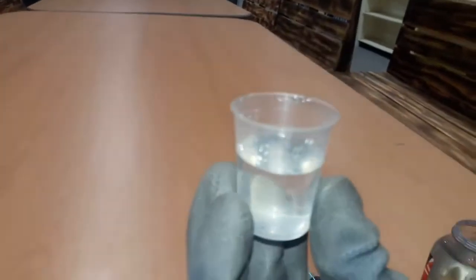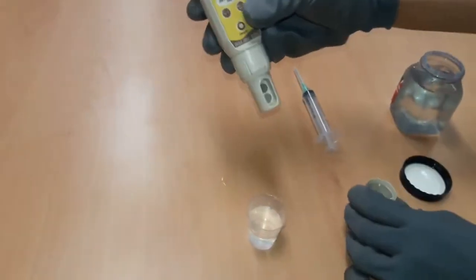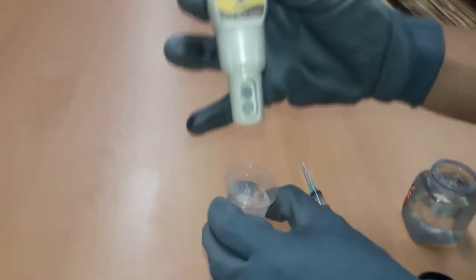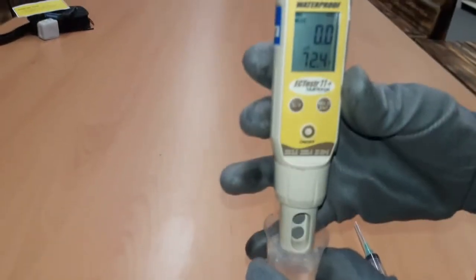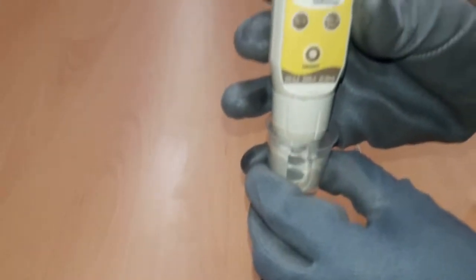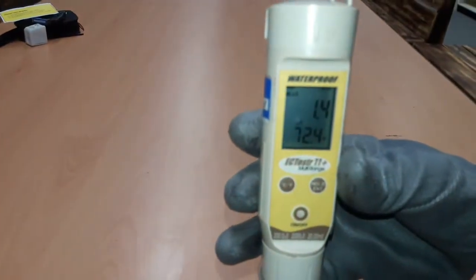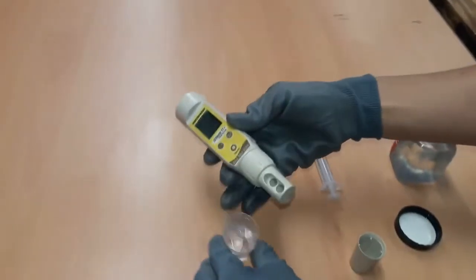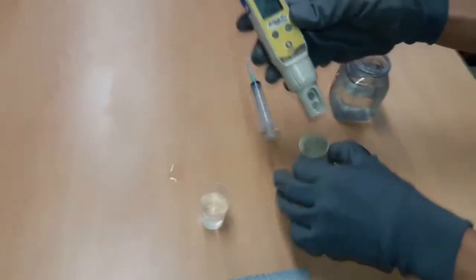Immerse the electrodes of the conductometer fully in the solvent in the beaker. Measure the conductivity of the distilled water and record the initial conductivity or reference value. Fill the syringe with 3 ml of solvent, or 1/4 of the solvent contained in the beaker.